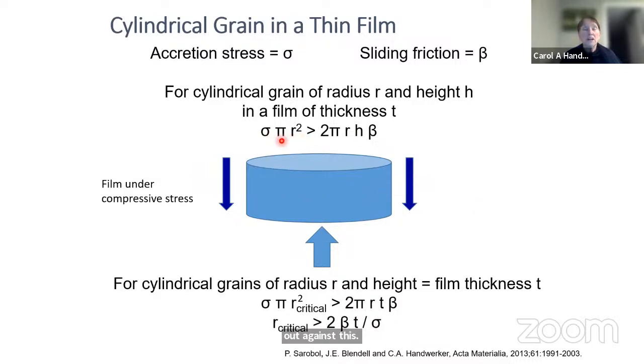So we did a simple calculation. This is the accretion stress. The force down here pushing it up is pi r squared times that stress, and it has to be greater than 2 pi r h, which is the cylindrical area, times the sliding friction. So it's a simple equation. For cylindrical grains where all these are constant, we come up with the prediction that there's a critical radius that relates the grain boundary sliding friction to the accretion stress, and it is proportional to the thickness. So this says that the grains have to actually be bigger than the average for this to happen.